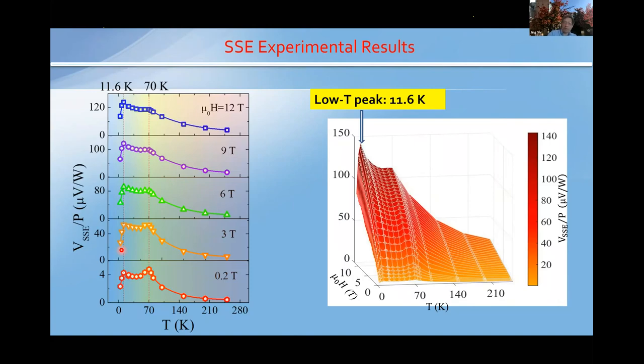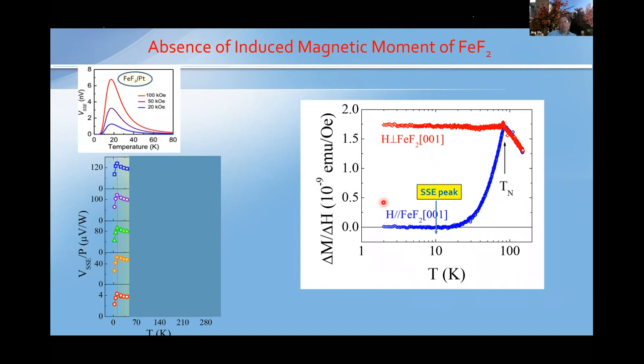So let's look at the induced moment. We measure the induced moment along both the easy axis direction and the hard axis direction. So these two curves are sort of reminiscent of the magnetic susceptibility that is anisotropic, right? But if I look at this temperature range here, where I see the low temperature peak, there is essentially zero induced moment. There's no induced moment in this temperature range, right?